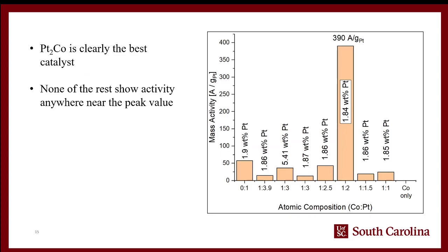So first I'm going to show the platinum cobalt data. I'll let the viewer guess which one is the best. It is very clearly platinum 2 cobalt. Everything else shows relatively little activity, whereas the platinum 2 cobalt is several times higher, anywhere from 5 to 10 times higher. This was repeated on 2 separate occasions, 2 different times on 2 different days. So it's not a fluke measurement.